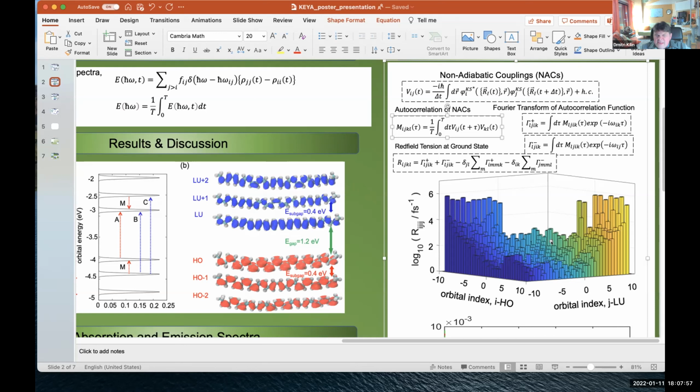There is no theorem, there is no guarantee that Fermi's golden rule will work all the time. True. And especially for soft organic materials, there is a very high chance that it will not work. So it's just good luck. But for small molecules with soft interatomic bonds, one may easily get oscillating autocorrelation functions, and the whole machinery may fail. So it is a proof.